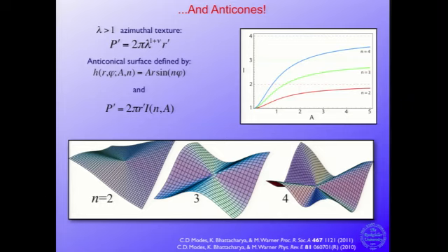Okay, so what about the other case where you had an azimuthal texture? So here the perimeters are getting longer and the radii are getting shorter, and so you must have some system with negative Gaussian curvature concentrated at a point. Mathematicians would just call this a cone again, but as a physicist, it felt like we should say something slightly different because we don't think of these crumpled shapes as cones. So we call them anticones.